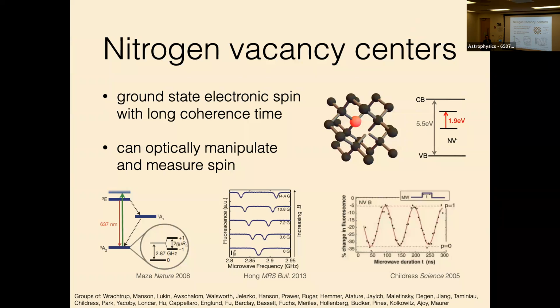So just by counting the total number of photons I get back, you can read out the spin sublevel. So you get this nice ODMR dip, and you can do things like read off the local magnetic field by looking for Zeeman splitting, and do coherent manipulations on the single electron spin.